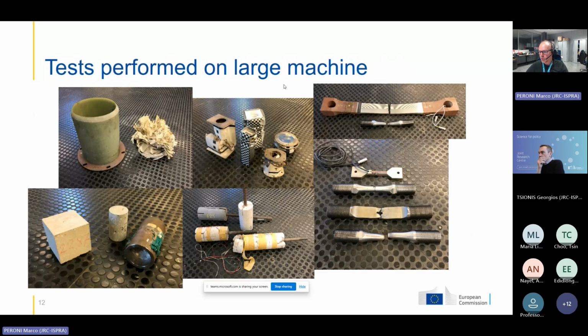Some tests that we did in the past with the machines are collected in this slide. You can see on the right the older specimens related to nuclear research, because our JRC started as a nuclear research center, and for example, these specimens were directly cut from a nuclear vessel. On the upper left side, you can see some specimens related to compression tests on automotive and train crash boxes or systems to absorb energy. These tests were done mainly in the 90s probably. And the tests at the bottom are more related to the civil sector, and you can see some test specimens for compression or for pull-out tests made on reinforced concrete parts.